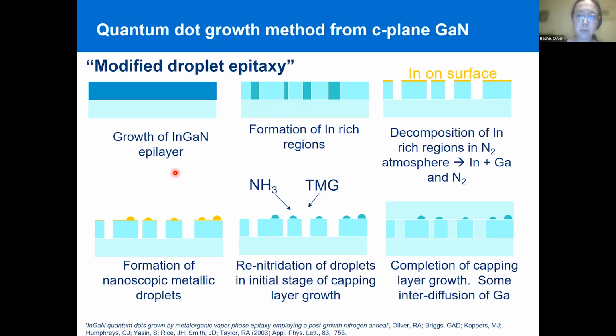Droplet epitaxy is where you deposit metal on the surface and let it ball up into droplets. And then you react it with your group 5 species, typically say arsenic in gallium arsenide, to form crystalline regions which will become quantum dots. In our technique, we start off with an indium gallium nitride thin layer. We anneal it to form indium-rich regions, and they decompose, leaving indium and indeed actually gallium on the surface. That then balls up into these tiny metallic droplets, and then we reintroduce ammonia and produce our indium gallium nitride crystals. As some interdiffusion goes on, the structures are somewhat chaotic.